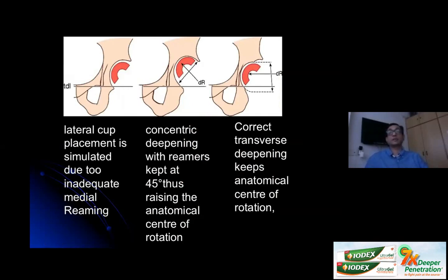The next step in doing a good hip, a cemented or an uncemented hip, either of them, would be to ream properly. The general mistake that everyone makes is to ream less, and you end up putting the cup which is far more lateral and inferior as compared to what you want to achieve. If you just keep on reaming in that same direction as you want to put your cup, like at 45 degrees inclination, you end up raising the center of the hip, and you end up putting the cup in at a much higher hip center than you need. So the ideal technique would be to first ream medially and then go superiorly in the inclination that you want to do.